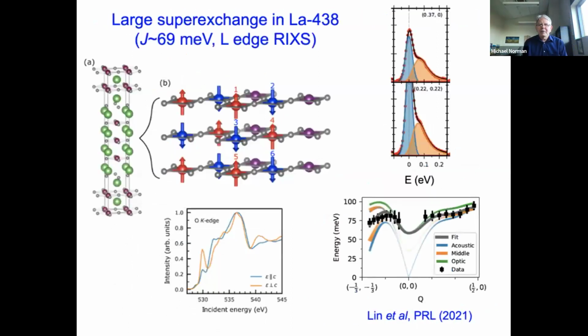Superexchange has been determined by this RIXS spectrum, and this is the magnon dispersion on the lower right that was determined by Mark Dean's group. As I said before, the lanthanum and praseodymium look very similar, except praseodymium is fuzzed out. And what you see is that you have a superexchange interaction, which is about 70 meV. So about half of that in cuprates, but still pretty substantial.